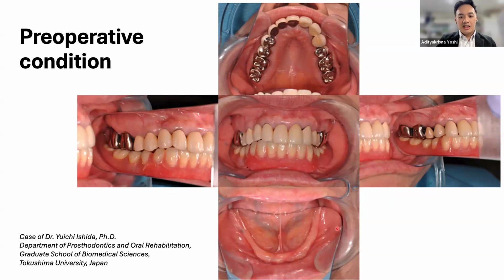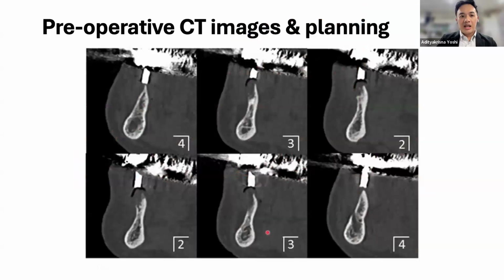So we can see here, there is only slight remaining alveolar bone. And then based on the preliminary CT images and treatment planning, there was insufficient bone thickness for the placement of the regular implant size. So it was decided to place a mini implant for the restoration of the mandible.